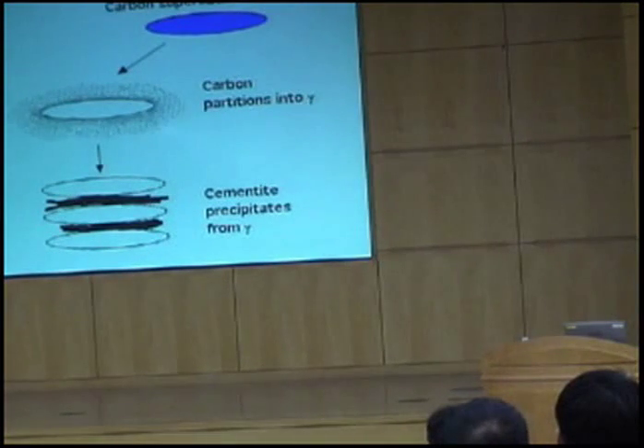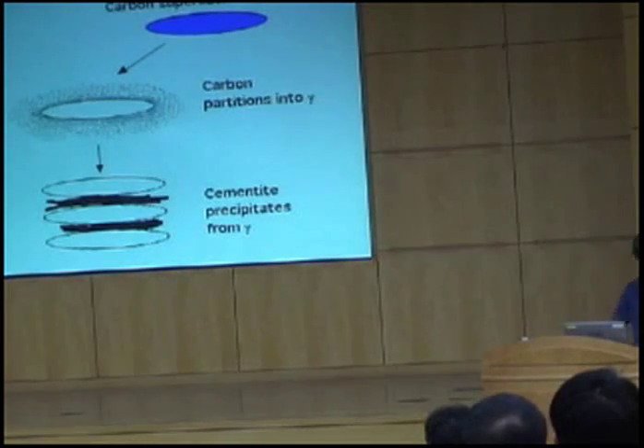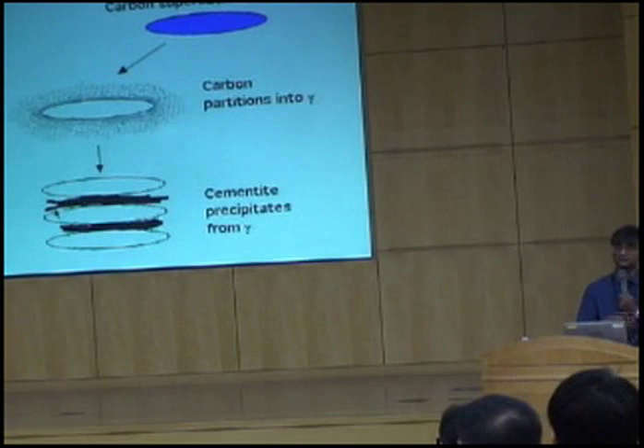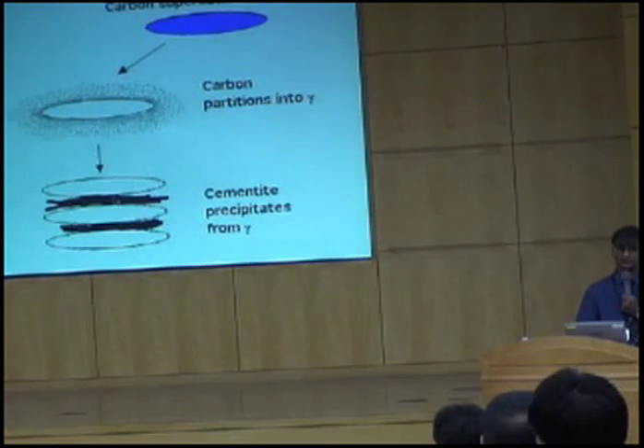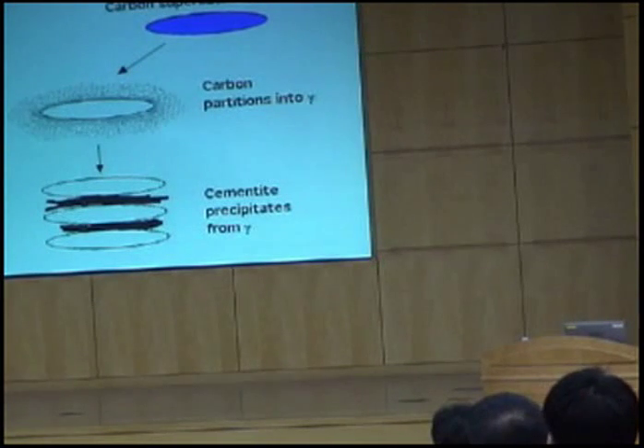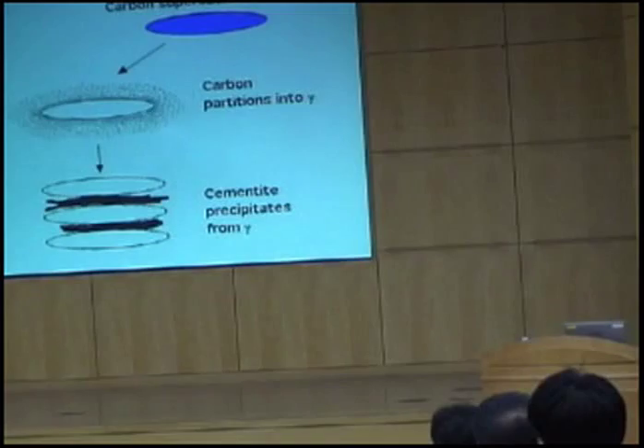Now, our focus is on bainitic steels, and I explained to you the mechanism of transformation yesterday. It basically happens in two stages: you have diffusionless growth, the carbon then partitions into austenite, and then we have precipitation of cementite. And this part is very bad for toughness, because we are not tempering the material deliberately. The cementite is forming during the course of the reaction, and it's coarse particles. So when we go into high-strength steels, the cementite is actually a bad phase to have there. It is a brittle phase with a very complicated crystal structure, and this is the main reason why bainitic steels have not competed against quenched and tempered martensitic steels for many, many years.